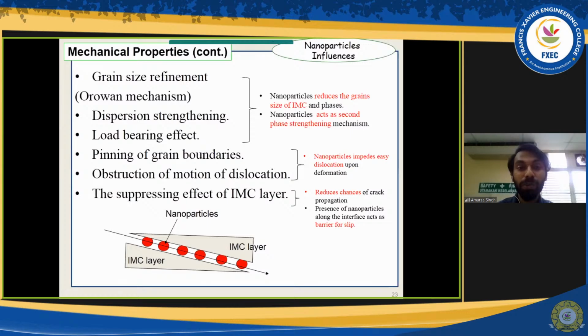Dispersion strengthening and the load bearing effect are also related to that particular concept. You can see I've highlighted what those three are related to. The fourth and fifth points are pinning of grain boundaries and obstruction of dislocation motion: the nanoparticles will be located along the grain boundary. So when stress is imposed, nanoparticles are hard materials. They cannot be penetrated. They have to be looped over, or they have to go around.